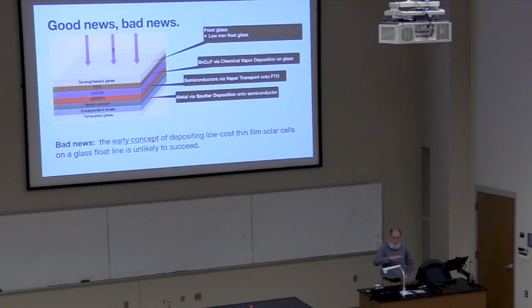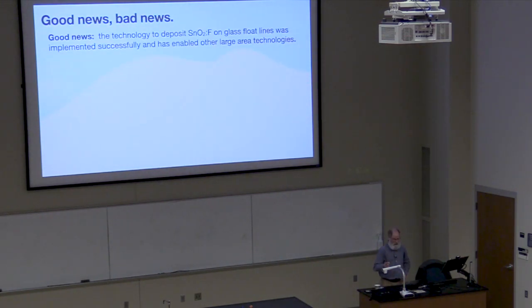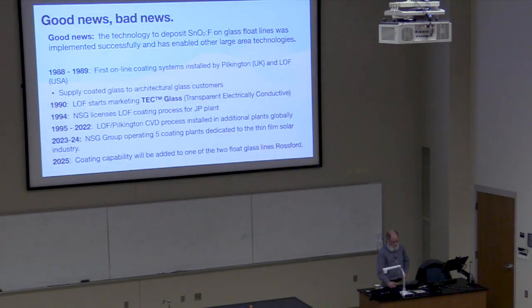So the bad news: the early concept that motivated this work was to deposit low-cost thin-film solar cells on the glass float line. It's probably not going to happen. The good news is that depositing fluorine-doped tin oxide on glass on float lines was implemented very successfully and has enabled some other technologies. This is just the history, and I want to focus on it because the first online coating systems were developed right here in Toledo by my engineering colleagues, and they were developed to supply architectural glass coatings.